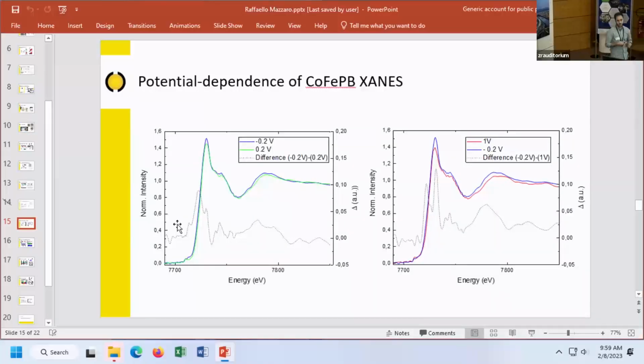Now we can have a look at what potential does to the catalyst, and here we have a comparison of the XANES spectra of the catalyst at negative potential, where we expect to have some reduction of the catalyst from cobalt 3 to cobalt 2, and the one we have at 0.2 and 1 volt, where no reduction is occurring, or is expected to be occurring. And as a consequence, you see that the spectrum at minus 0.2 is always showing a small shift toward lower energy, and also an increased white line, which can be assigned to an increased density of states in the cobalt center. So probably due to the reduction itself of the system.